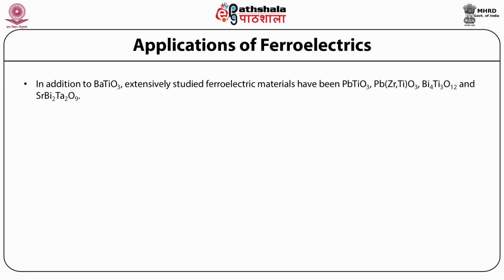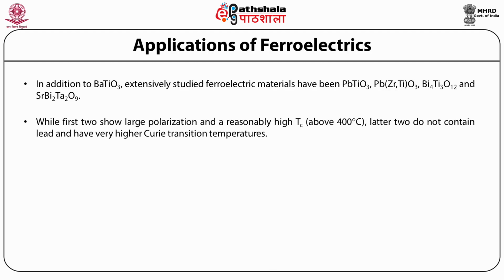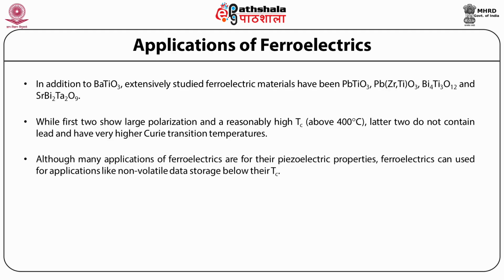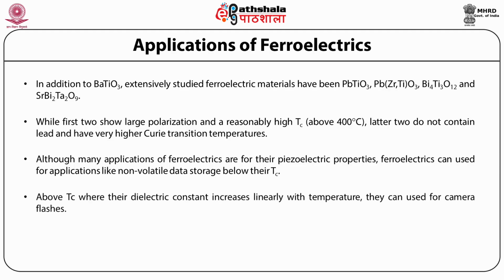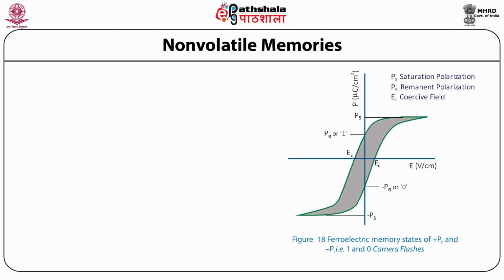Application of ferroelectrics. In addition to barium titanate, extensively studied ferroelectric materials have been lead titanate, lead zirconium titanate, bismuth titanate and strontium bismuth tantalate. While the first two show large polarization and a reasonably high Curie temperature, the latter two do not have lead and have very high Curie transition temperature. Although many applications of ferroelectrics are for their piezoelectric properties, ferroelectrics can be used for applications like non-volatile data storage below their TC, whereas above TC, where their dielectric constant increases linearly with temperature, they can be used for camera flashes. So the first application is non-volatile memories.